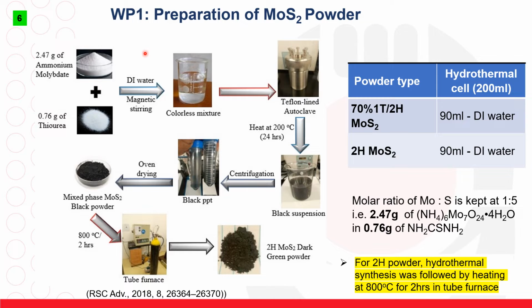For the first work package, we started with blending ammonium molybdate, which was the source of our molybdenum, and thiourea, which was the source of sulfur, with deionized water, and then used the hydrothermal technique, or the hydrothermal cell, to heat. We heated it at 200 degrees Celsius for 24 hours to form mixed phase molybdenum disulfide. And this molybdenum disulfide prepared in this way had 70% of 1T phase in the 2H phase. Further processing involved drying of this black powder, and if we extended the processing by heating this powder at 800 degrees Celsius for 2 hours, the resultant was the single phase 2H molybdenum disulfide nanosheets.